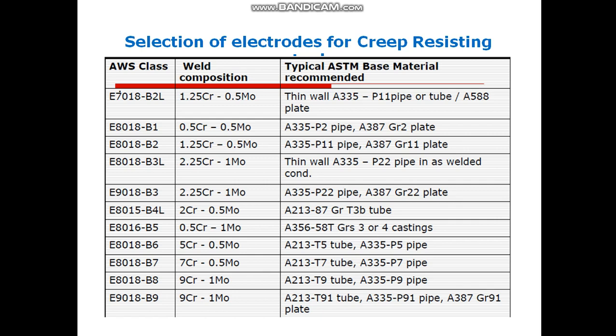So here, E7018 B2, B2L: here E stands for electrode, 70 is the kilopound per square inch, so 70,000 pounds per square inch. 1 is the welding position, flat, horizontal, vertical, overhead, except vertical down, and 8 is the type of coating, and these B2, B3, B4 are the chemical composition of the deposited weld metal. The table gives the selection of electrodes for different creep resisting materials.